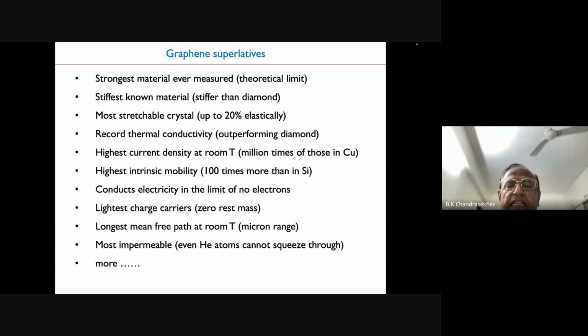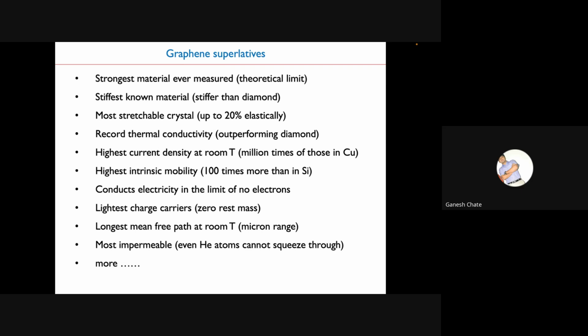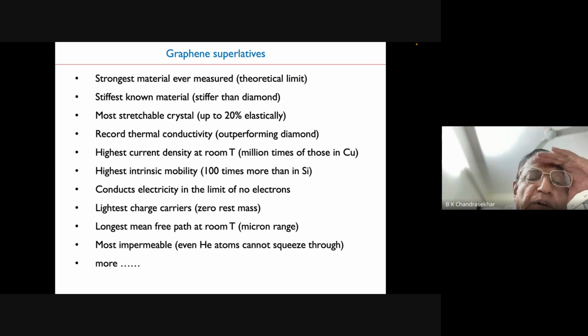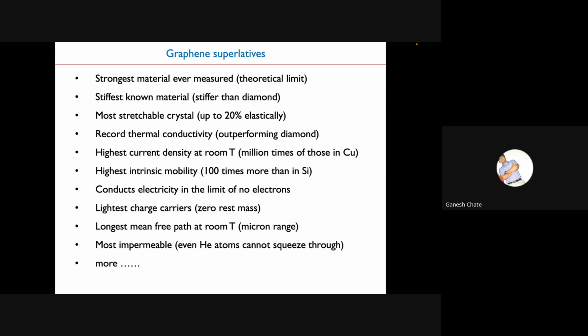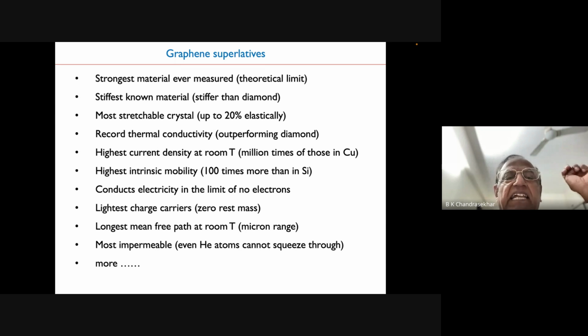I think any carbon material will react around 500, 600 degrees centigrade. But if we are working at room temperature without any control of the atmosphere, in regular atmosphere - if you do it in air, what will happen is graphene will become graphene oxide. So the advantage of graphene is lost. Even if the working temperatures are around 300, 350, 400 degrees, I would say that slowly it will start oxidizing. It is a question of rate of reaction. Even at 300 degrees centigrade, I am sure the graphene will start reacting. May not be very high, but still it will become oxidized.